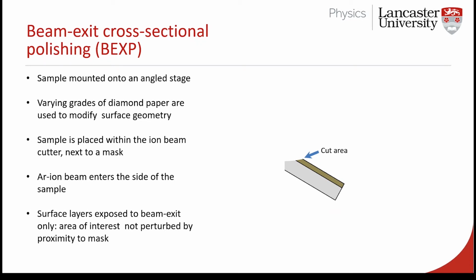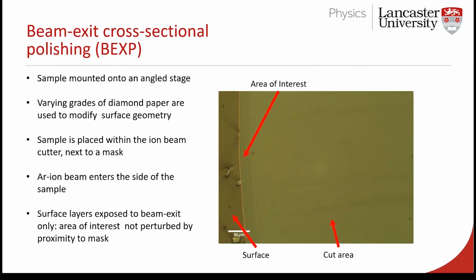And what we can see when we look at this is we get this long, flat, smooth, clean cut area. It's been elongated, okay? So we have the cut area, we have the bulk substrate. You can see on this side, we have our nasty, horrible surface that no one really cares about on this side. But we now have this nice, big, clean, flat area that has been cut in the middle. Much deeper than we would normally be able to access with scanning probe microscopy, but now it's absolutely there for the characterization.